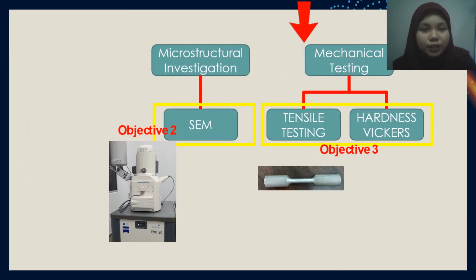And then for the microstructural investigation, SEM or scanning electron microscopy as the second objective was by applying 150 times magnification, and I observed the overall morphological state of the samples for the as-cast, for the THIXOFORMED and the THIXOFORMED heat-treated samples.